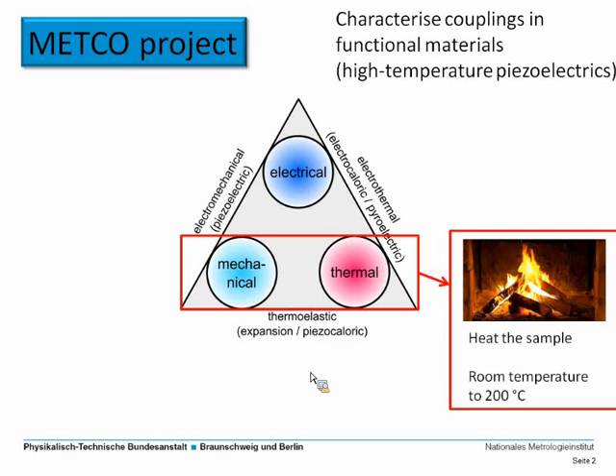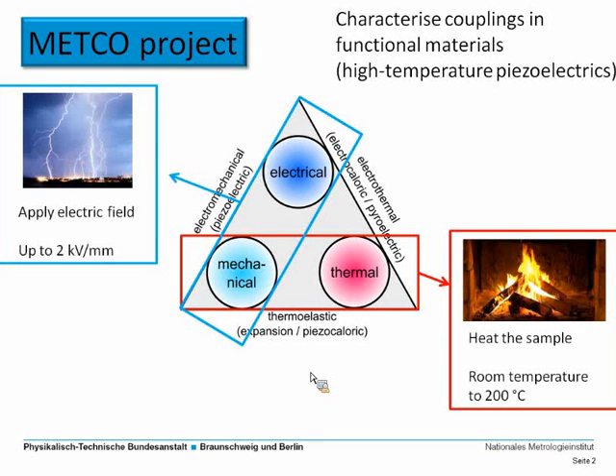We're aiming at a temperature range between room temperature and 200 degrees centigrade. And if we want to see the connection between the electrical and mechanical properties, so in this case the piezoelectric actuation, we have to be able to apply an electric field with voltages in the order of a couple of kilovolts so that we can reach maximum fields of 2 kilovolts per millimeter. So the first step in the project was to devise and fabricate a novel sample environment for this case.